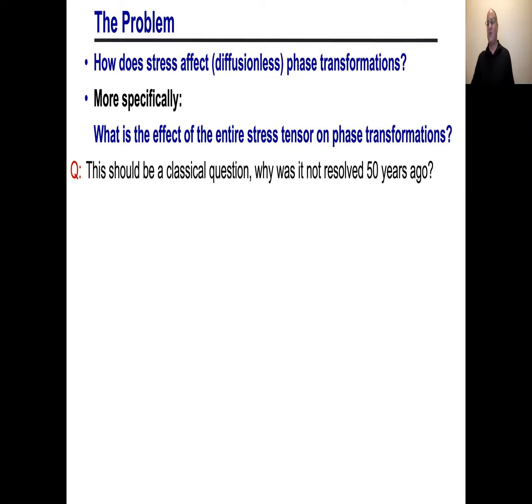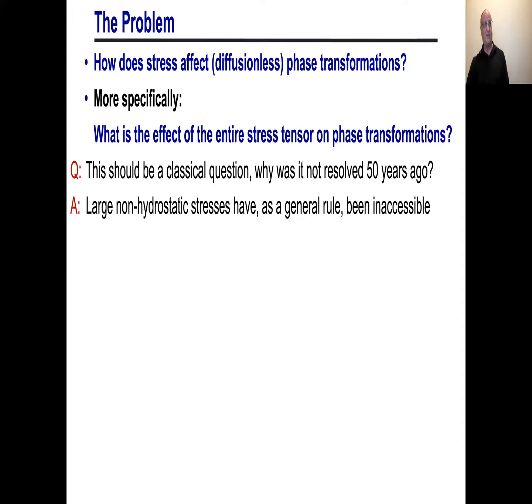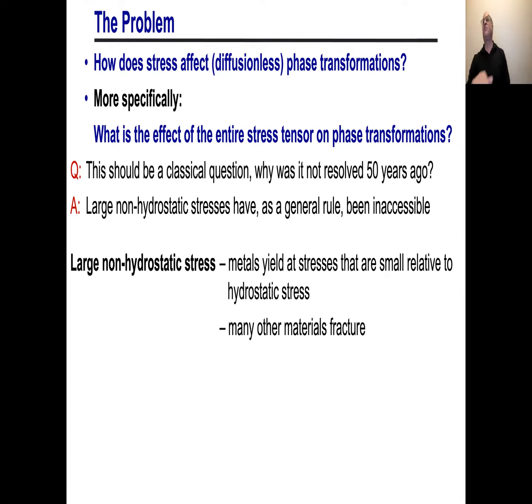Well, there have actually been quite a few people who have looked at this over the years. But I would say it really hasn't been a very serious question up until now. And the real reason for it is that in materials, large non-hydrostatic or shear stresses, as a general rule, have been inaccessible. And why is that? Well, very simply, as compared to these large hydrostatic stresses we can apply, metals tend to have yield stresses which are much, much smaller than the values that I was quoting before. And if I'm not dealing with metals, many materials with large shear stresses will just fracture before you get up to very large non-hydrostatic stresses.